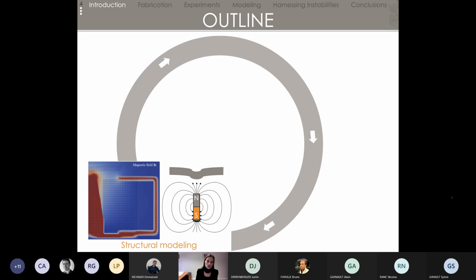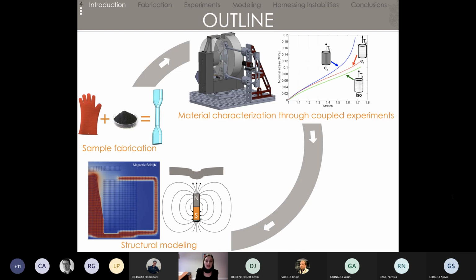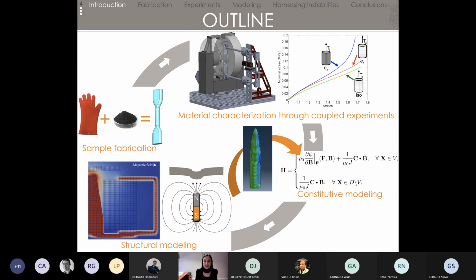So we have a constitutive law, and so we can finally address the question of structural modeling, and propose devices made with those magnetorheological elastomers. For that, we started from the beginning: sample fabrication, then material characterization under coupled magnetomechanical loading, so that we had enough data to obtain the parameters of a phenomenological model that I will show after. The only issue we encountered is that when we tried to identify those parameters, we realized that those materials were suffering from structural effects, which means you cannot identify their behavior just analytically. You will need to add a step where you identify everything via finite element.